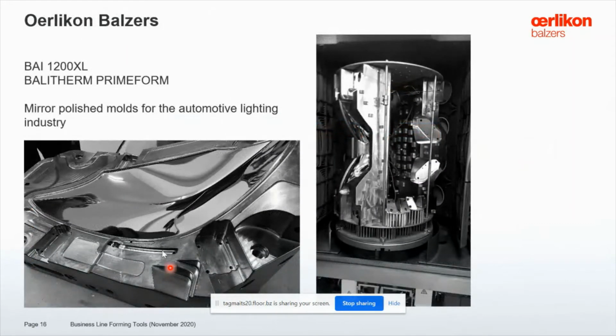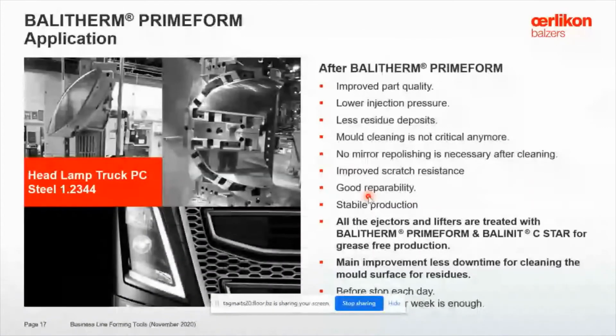For example, we are working together on mirror polished molds for automotive big lighting molds. And you can see here the level of polishing which is maintained. And we are coating these molds in a typical coating cycle. You can see here the picture. So after BALITHERM PRIMEFORM, the customer experienced improved part quality, lower injection pressure, less residue deposits because the treatment itself forms a protective layer and separates the melt from the tools. The mold cleaning cycles or intervals between maintenance is significantly increased.